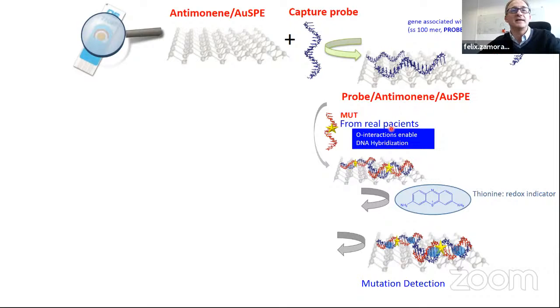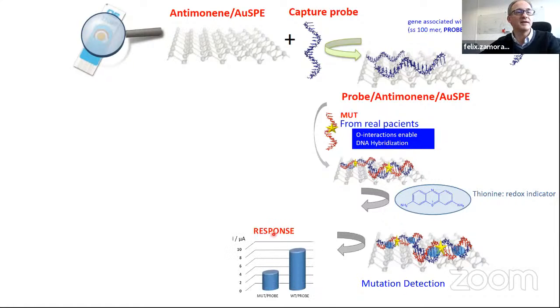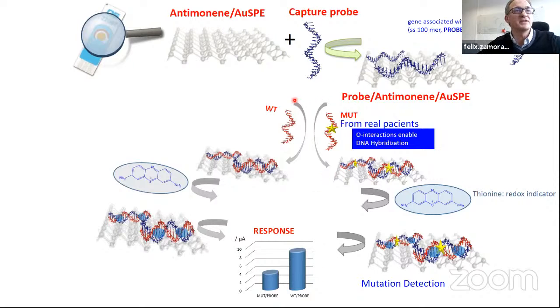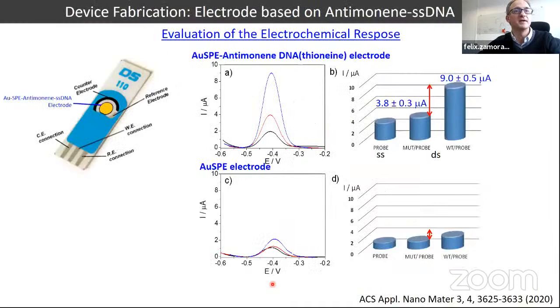So in here we use single-strand DNAs coming from real patients from La Paz Hospital. And when you put the sensor in contact with these single-strand DNA sequences coming from patients having this cancer, then we observe that you have hybridization, and then you have a nice electrochemical response, which is nicer if you compare with the result that we got when you instead use what we call wild type single-strand DNA coming from people without this cancer. When you treat our sensor with this single-strand DNA, we observe a very different electrochemical response.